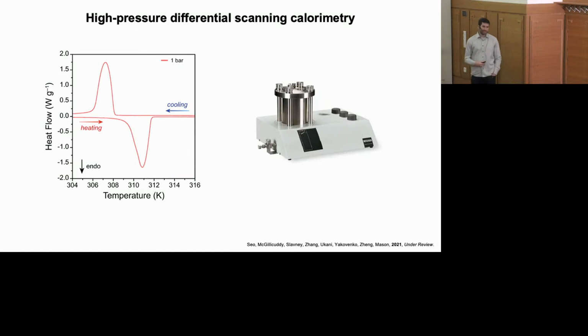So in order to evaluate the phase change thermodynamics, so how the entropy and enthalpy and transition temperature change as a function of applying pressure, we perform experiments that are known as differential scanning calorimetry experiments. So these are experiments where we're at a constant pressure and we're changing the temperature of our material and monitoring the flow of heat in the system. So simple kind of calorimetry experiments where you are measuring the thermodynamics associated with the phase transition.